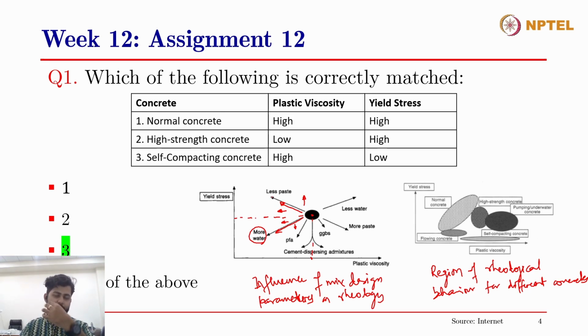That is the case when, if you can imagine, you lower the paste content, you'd see a lower slump value. So imagine a pumpable concrete, and now you have decreased the paste content, and you have made, let's say, a roller compacted concrete, which has a zero slump. Even the roller compacted concrete can still be pumped to a distance, even though it'll probably require some higher energy, but you'll be able to pump it. But still, the yield stress is very high, and therefore you're achieving a very low slump in that case, right? So this is what happens when you lower the paste content.